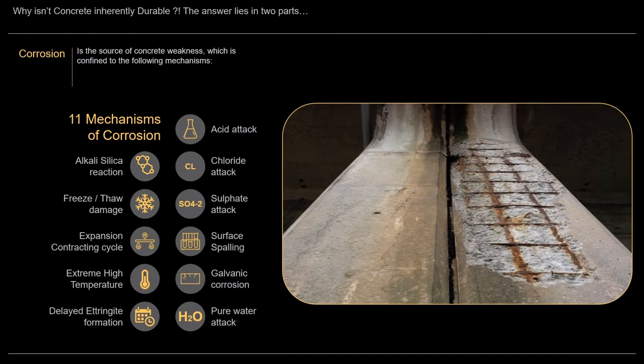It decalcifies concrete and it leaches the lime out of concrete and causes embrittlement. So there's 11 mechanisms of potential corrosion to concrete. And as I said, one common denominator, water. If we keep water out of concrete, not only do we keep our tunnels dry, but we stop every single known mechanism of corrosion.